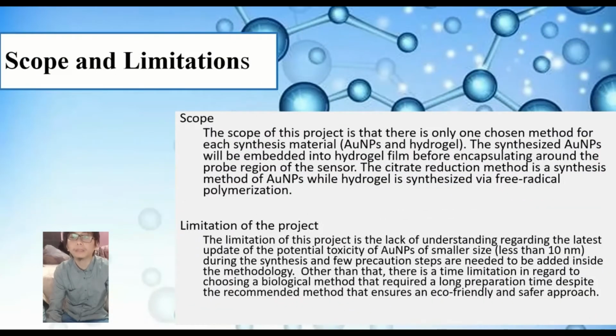The scope and limitation of this proposal. The scope of this project is that there is only one chosen method for each synthesis material, which is for the nanoparticles and the hydrogels. The synthesized nanoparticles will be embedded into a hydrogel film before encapsulating around the probe region of the sensor. The citrate reduction method is the synthesis method for the nanoparticles, while the hydrogel is synthesized via free radical polymerization.